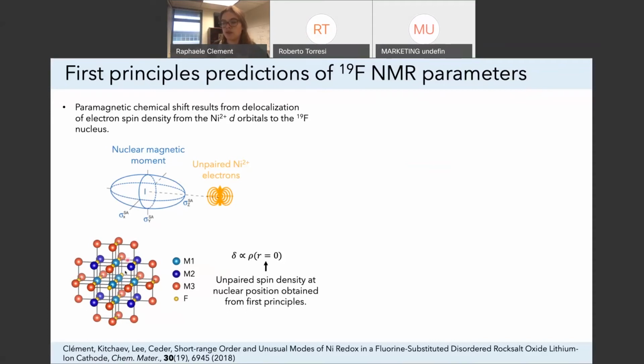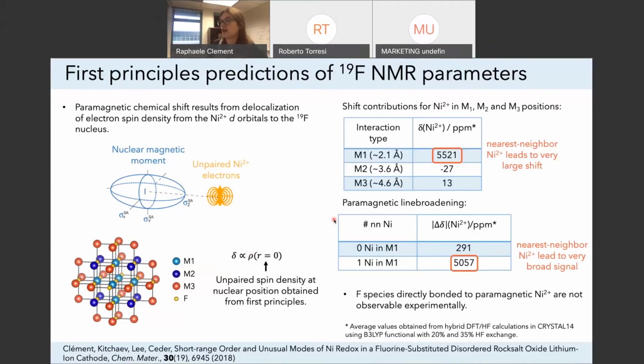So what I'm going to show you right now is what happens when you have nickel directly bonded to fluorine, or what happens when it's further away from the fluorine in the second coordination shell or the third coordination shell. What we found from DFT is that if it is directly bonded to fluorine, it will lead to a very large chemical shift and a very broad signal. If it's further away, so in the M2 position, M3 position, which are your second coordination shell and third coordination shell, the chemical shift should be much smaller, and the broadening is not as significant.